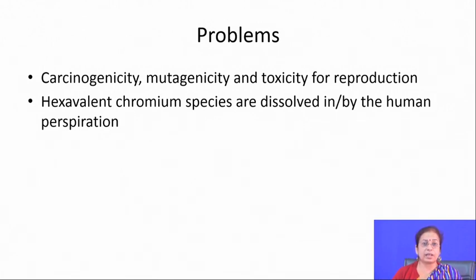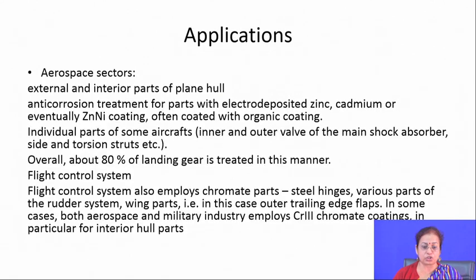But as I mentioned, this zinc chromate solution is not environment friendly. So, there is problem of carcinogenicity or mutagenicity or toxicity, and they are sometimes dissolved in human perspiration. So, this chromate coating these days is replaced by phosphate coating to a large extent. But in some sectors it has application, like aerospace sectors, where prior to application of painting this particular coating is applied to a large extent.